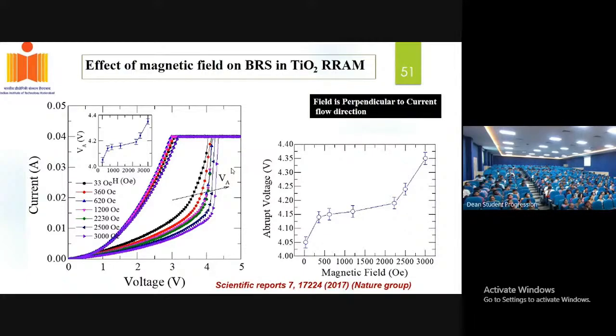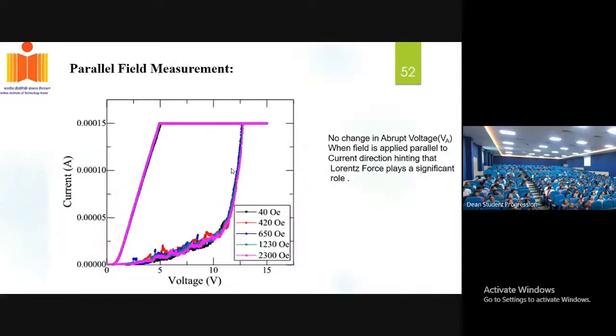As you could see here, the voltage at which the device goes from high resistance to the low resistance state has been shifted with the strength of the magnetic field. As you could see here, we also plotted the magnetic field versus the abrupt voltage. So we do see a significant enhancement in the voltage. We need to apply more amount of voltage to switch the device from the high resistance state to the low resistance. However, we also try to do another experiment to prove that the Lorentz force is the one which causes this kind of shifting.